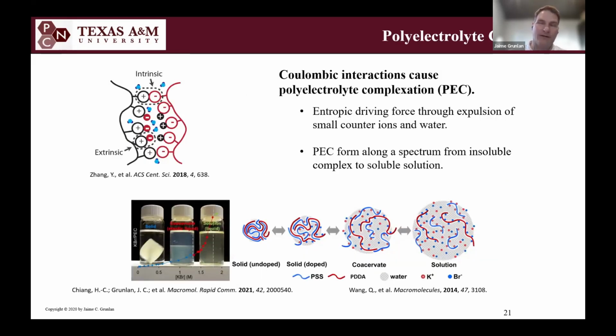Before I go deep into that, I wanted to highlight a parallel technique that we do instead of layer by layer assembly, where sometimes I need 30, 40, 50 layers to get a good property. If I'm careful with how I put my positive and negatively charged ingredients together, I can make a suspension called a coacervate. It's almost like a polymer emulsion, but of loosely bound cationic and anionic components. And if one of my 2 ingredients, or if I have more ingredients, some of them are pH responsive, where they'll turn the charge off at a certain pH, you can make these stable solutions or suspensions that can be used as the starting point for a single coating system instead of a multiple layer coating system.